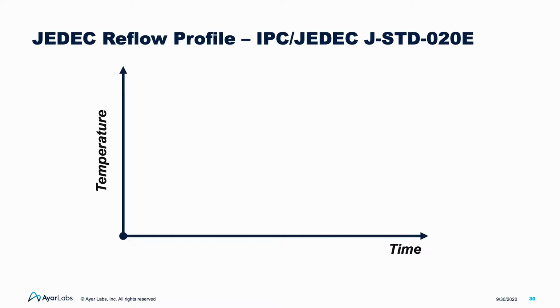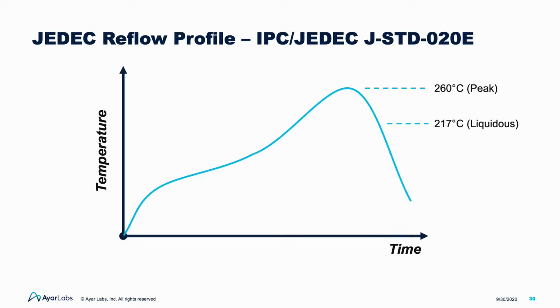What is the standard reflow profile? This is an example thermal profile as defined by the IPC and JEDEC. Note that the profile has an initial soak period with a final peak temperature at 260 degrees C. Note that the process is relatively short, with the room temperature to peak temperature time not to exceed 8 minutes. This profile is suitable for leadless solders. However, the industry has also developed so-called low temperature solders, many of which have a liquidus temperature below 200 degrees C. Materials and process development of these solders are very interesting for applications such as in-package photonics.